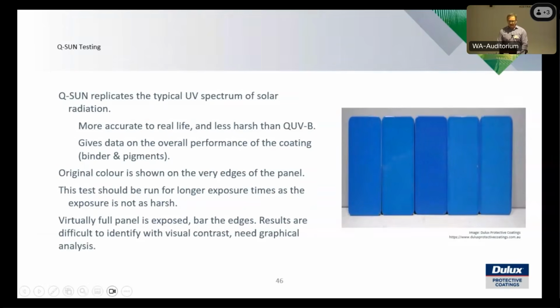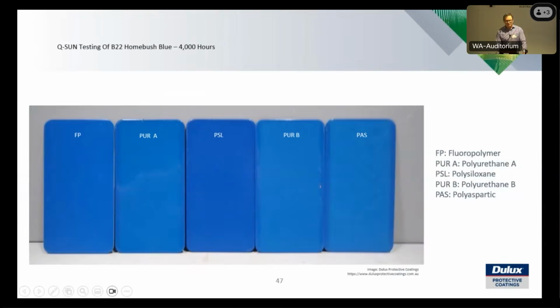The Q-Sun testing is a little bit different. So pretty much that whole panel there is tested. So it's only really the outside of that panel which you'll be able to visually see any colour change from. But as you can see, after 4,000 hours, the fluoropolymer hasn't really changed as much. If you look back at the polyaspartic and the polyurethanes, there is some change compared to the edges of those panels. Polysiloxane is still looking quite a good option in that blue there as well.